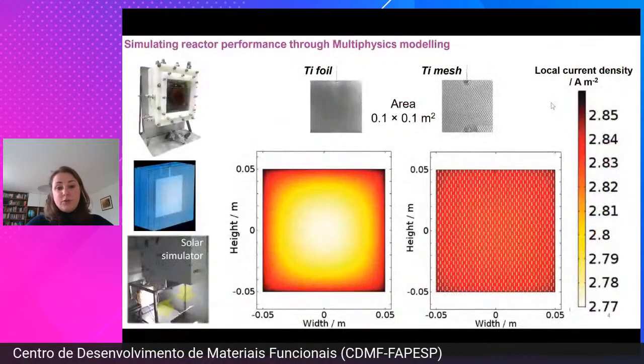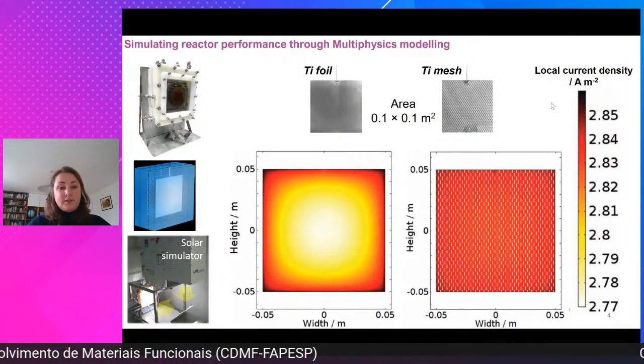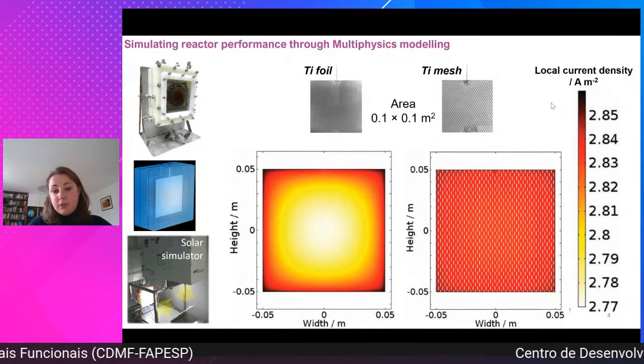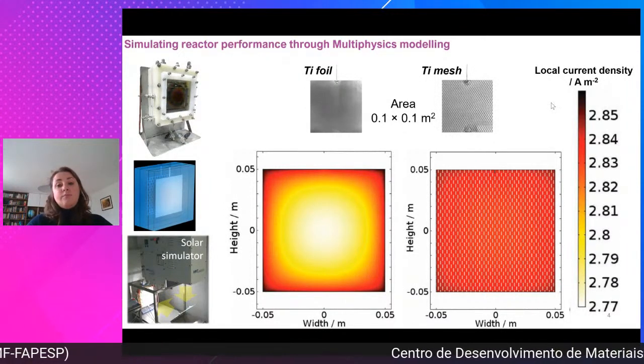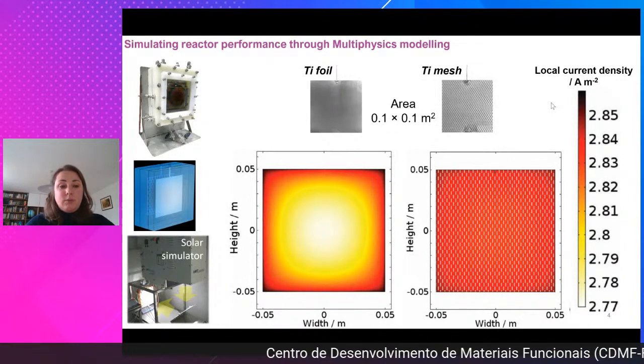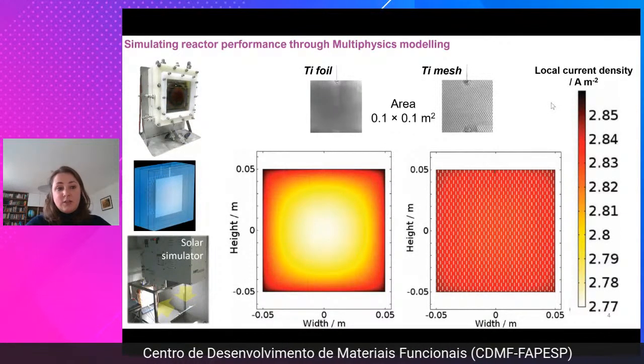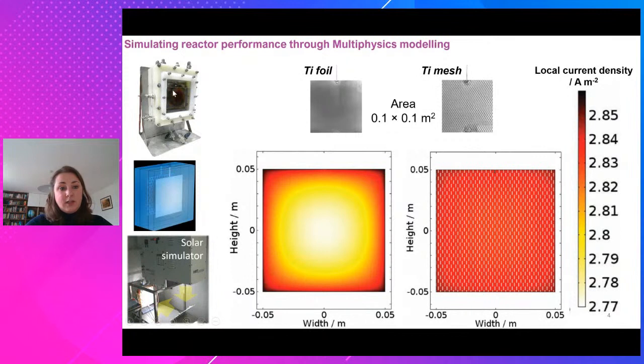So what we do is we always compare our multi-physics models, which we carry out in COMSOL Multiphysics, to experimental measurements. We have several reactors that are designed to incorporate upscaled electrodes. On the top left is a reactor that houses a 10 by 10 centimeter hematite electrode, which we made by spray pyrolysis. And we compared some performance of a planar and a perforated electrode to see whether the perforations can homogenize the current.